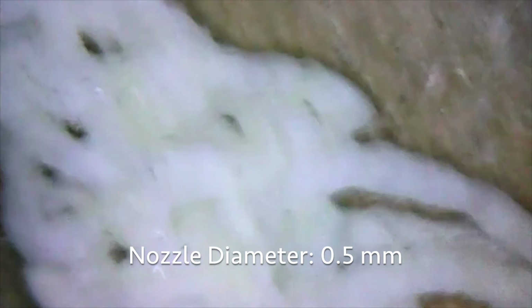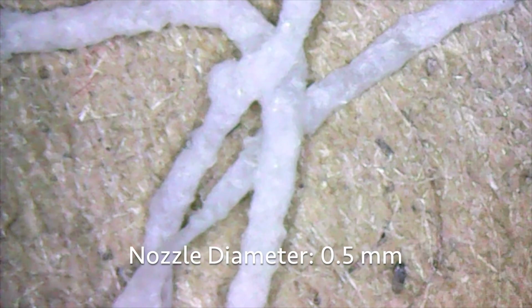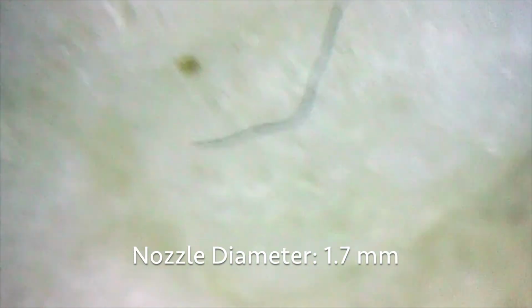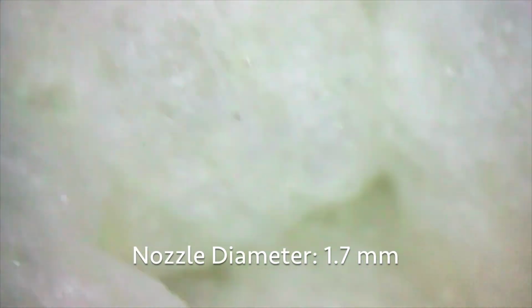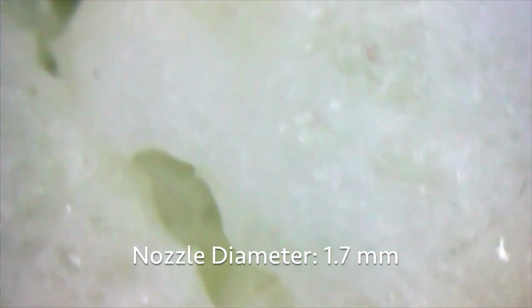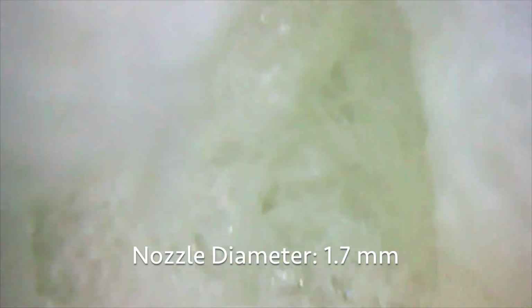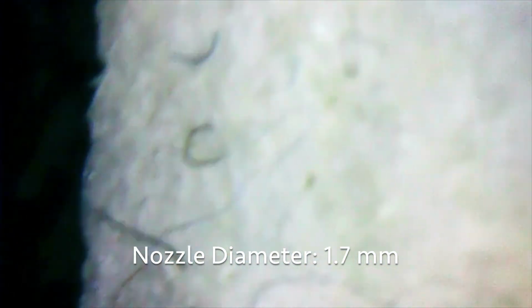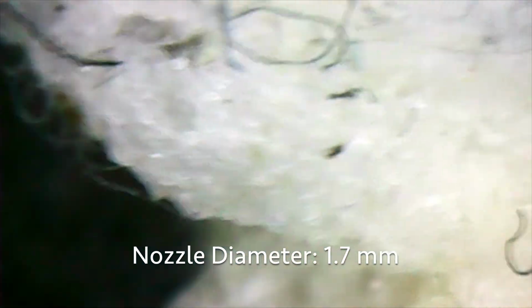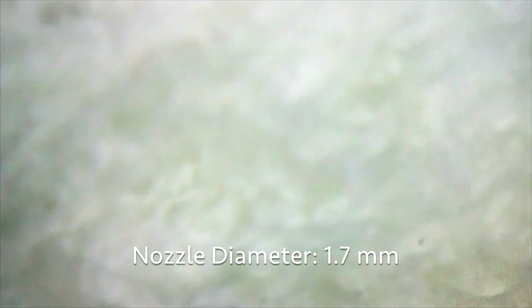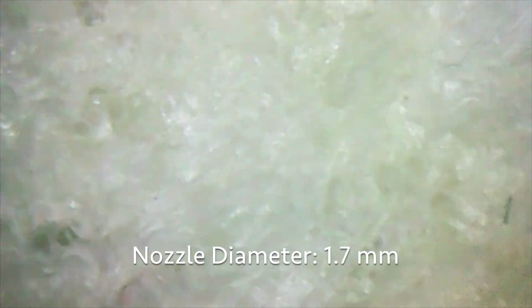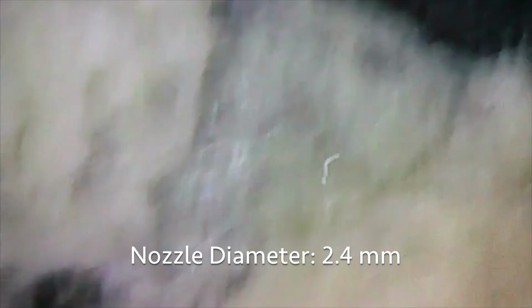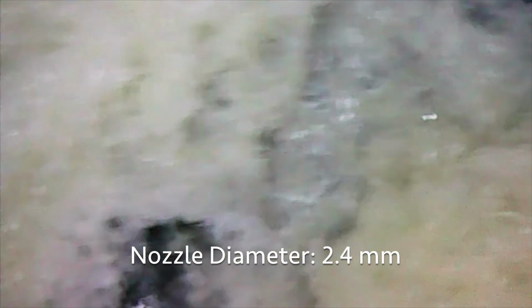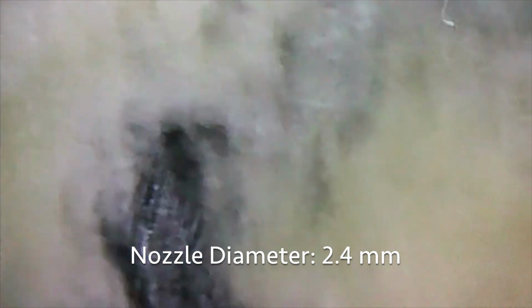However, I wanted to take this under a microscope and see how the Kevlar was distributed throughout the webbing. Now it was clear with the smallest diameter sample, you could see clumps of Kevlar. This improved in the webbing that was shot out of larger diameters, but it still seemed like there were areas where there were clumps of Kevlar. So if you think about it, if the fluid flows just fine through the nozzle, and then the Kevlar is introduced, right? A solid, a colloid, essentially. It can't move through the nozzle as effectively if it's not flowing homogeneously, and so you see these clumps. And that probably does not do great things for the strength of this webbing.